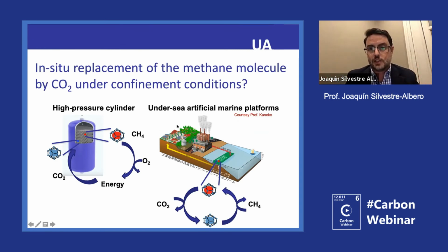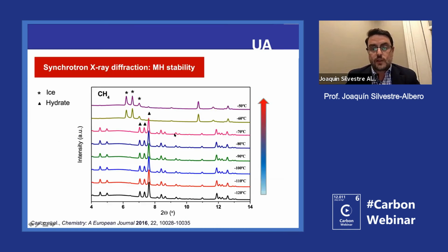And this is a picture from Professor Katsumi Kaneko, explaining that maybe we can use artificial platforms where we can store methane in the form of gas hydrate and at a certain moment replace the methane by CO2. The only option to do this experiment was to go to the synchrotron. The first thing we wanted to do is to check the stability of the hydrate, because I have to make them, and at a certain moment, I have to pump the system and put in CO2. So the first experiment is to see how stable these methane hydrates are.